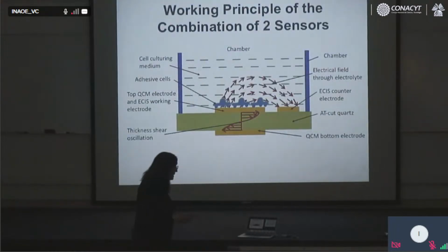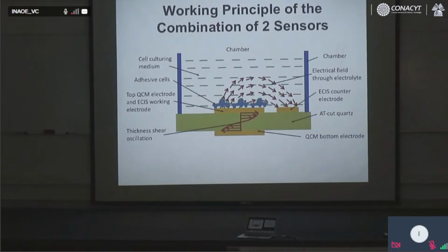Now, here is the quartz crystal with the impedance spectroscopy. This is a sketch of my idea, and we can see a combination of two sensors. First, let's look at the quartz crystal microbalance, which is a very common device, very well known, very developed. It has the quartz substrate and the upper QCM electrode. You need two electrodes to produce the acoustic wave, and the acoustic wave looks like that inside the quartz substrate.